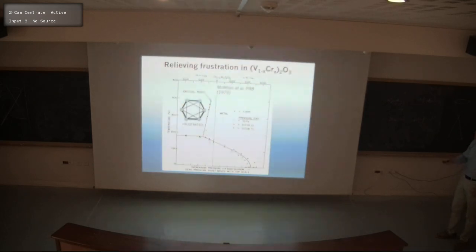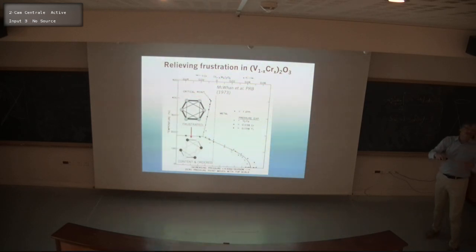ordered state. So basically, what we think is happening is that we have a highly frustrated spin system in the paramagnetic insulator, and in fact you can trace it to the honeycomb lattice with competing near and next-near neighbor interactions, and extremely short correlations exist there. When we then cool it down, the lattice basically gives way.